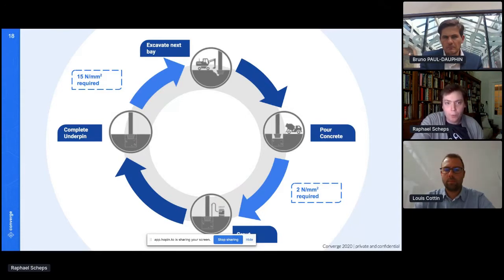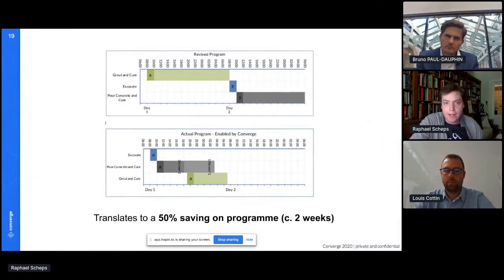We were then having to wait for the underpinning to complete and for the concrete to reach a strength of 15 MPa before you could excavate the next bay. And so that whole cycle was completely concrete dependent. And as you can see on the slides, we were able to demonstrate and move from a 2-day cycle to a 1-day cycle. So Taylor Woodrow worked in additional shifts and was able to actually create a 50% saving on program, which on that month-long construction schedule was able to actually save about 2 weeks, which is huge, both in regards to the operation of the structure, but also in regards to just delivering on time and optimizing efficiencies on the sites.